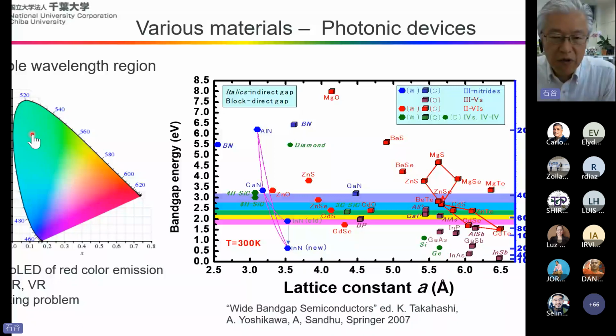Okay, but for the monolithic growth for micro LEDs for AR and VR, high indium content gallium indium nitride is desired. But it is very difficult because of the large lattice mismatching between gallium nitride and indium nitride. That is about 11%. So this is a very, very high lattice mismatch.